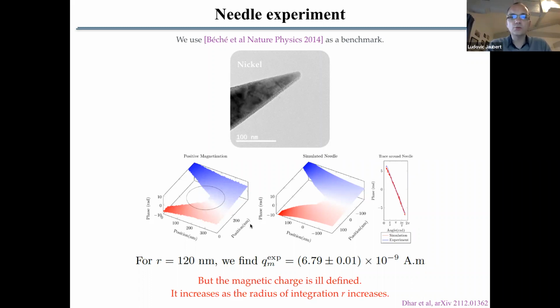Yeah. And so to comment on that, the additional thing that we did here in Okinawa compared to this initial paper is that we heated up the material. So we heated up nickel above its Curie temperature, so it became a paramagnet, and we could see that indeed this phase shift disappeared when we were beyond the Curie point. So we show that this phase shift is really coming from the magnetic moment of the nickel sample here, because when you heat it to make it paramagnet, it disappears.